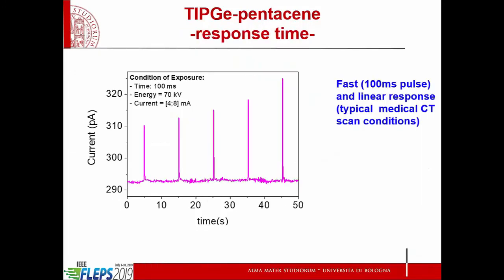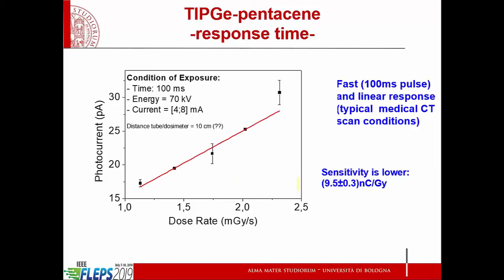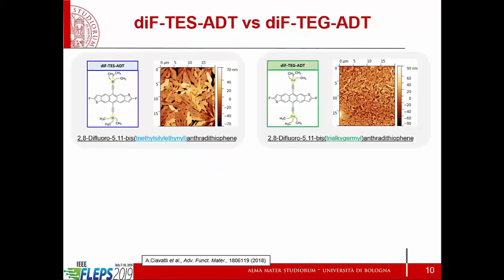Here we go with the response time, and that is what I wanted to mention before. So that is the on-off with the very, very fast on, as you can see it here, response of a TIPGe-pentacene thin film. What is the on? The on is a beam which has a higher energy, about 70 kilovolt, and the on pulse is 100 milliseconds. This measurement has been carried out in a hospital under a CT scan. So to test if this device could reliably at least be used to monitor very fast pulses. And it does, because you can detect clearly the signal, even though the sensitivity is much lower because you're not collecting all of the charge. So there's a trade-off. You can get either a fast response or a high sensitivity, and again, it depends on the application you target.